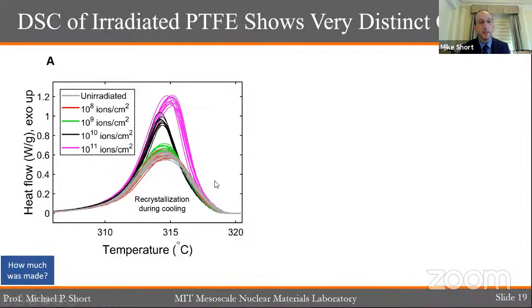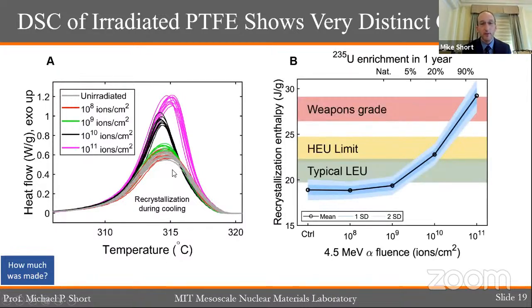So when we look at these peak signals as a function of irradiation fluence here, you can see that the difference between the gray and the red, which is very lightly irradiated, you can't really see a difference. They're roughly coincident. But as we continue irradiating, these peaks start to separate. And when we do some statistics on these to look at the average and standard deviation of the enthalpies of recrystallization, we get our final result, which is that we can distinguish one bomb's worth of special nuclear material, and we can tell its enrichment very, very well.